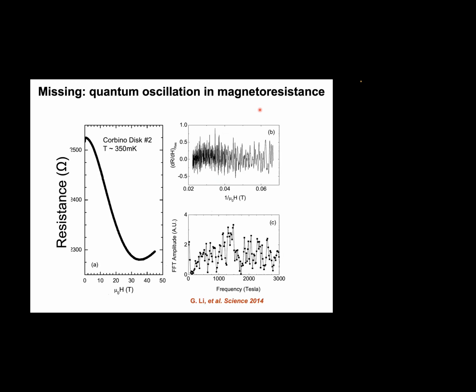But basically, we thought we knew something would go on. We just need to carry out strong fields and try looking for oscillations out of that metallic surface, right? And they say this is topological protection. We should see something, right? And yet we got the best device, the best Hall bar, in this case actually the best Corbino disk geometry device. We went to the strongest DC magnetic fields on Earth. This is Tallahassee, Florida, where we were able to go up to 45 Tesla. We had a few failures in the magnets, but eventually we ran up to 45 Tesla, and nothing happened.